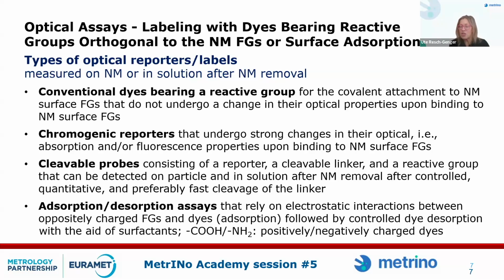You can also go for chromogenic reporters. These are dyes which undergo a strong change in their optical properties upon interacting or upon reacting with a functional group on the nanoparticle surface. Thereby, the absorption and fluorescence properties are changed. So you can distinguish where your reporter has been sitting. Then there's another type of probe, cleavable probes, taken from pharmaceutical industries or drug delivery systems. Here you have a cleavable linker, a reactive group, and a reporter group, and these probes can be detected on the particle and in solution. And eventually, adsorption-desorption assays, which rely on electrostatic interactions. So you have a negatively charged particle interacting with a positively charged dye and vice versa.